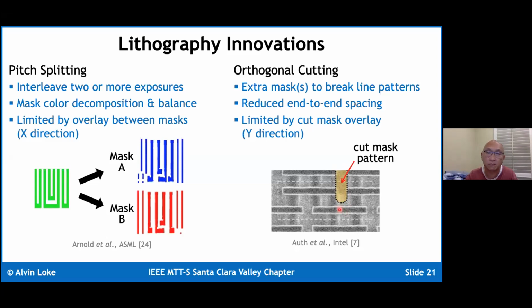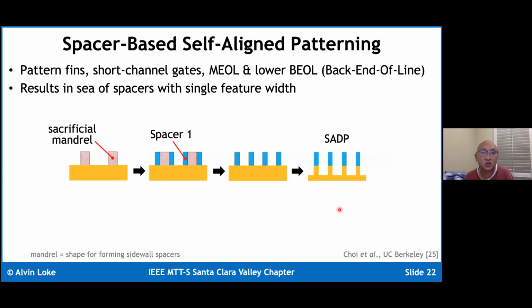Okay, so as you might expect, the industry has been working towards self-aligned approaches, which are essentially insensitive to misalignment. This is the way fins are patterned. Short channel gates, middle end of line, lower back end of line, they're all patterned this way. So the idea here is you want to pattern a sea of spacers, which you then use as a hard mask for patterning your underlying layer.